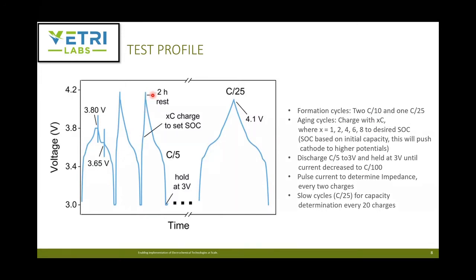They took the state of charge and then discharged at C over 5, held it at 3 volts until the current dropped to C over 100. So that has been the whole time. So C over 5 until 3 volts, and then once 3 volts is reached, until the current decreased to C over 100, and then started the charging cycle again.